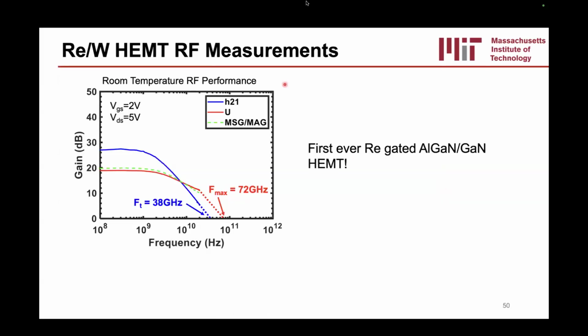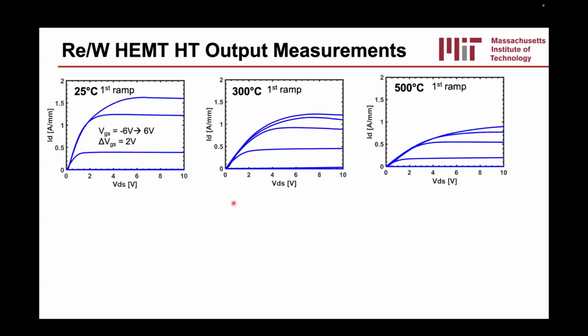Alrighty, so then we made the first ever rhenium-gated AlGaN HEMTs, and measured the frequency performance. In this case, it was a relatively long channel, with 200 nanometer gate lengths. So the FT was about 38 gigahertz, Fmax was about 72 gigahertz at room temperature. And then we measured the output characteristics as a function of temperature from 25 to 500 C. We can see once again, the current drops not a whole lot, about 2x once again.